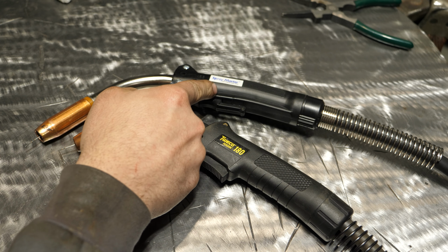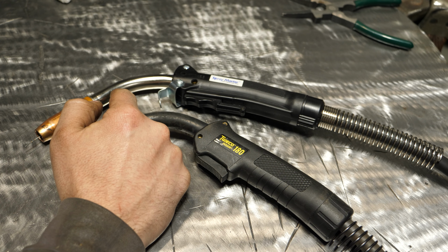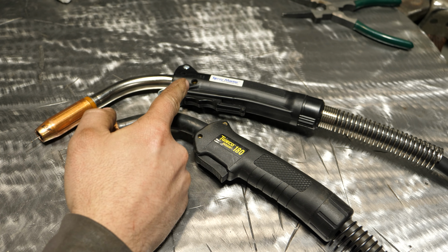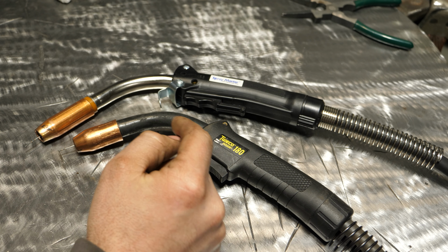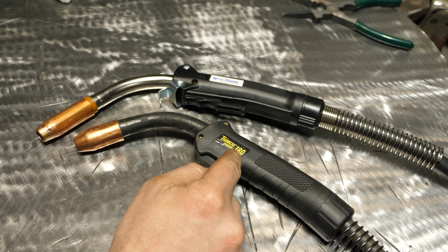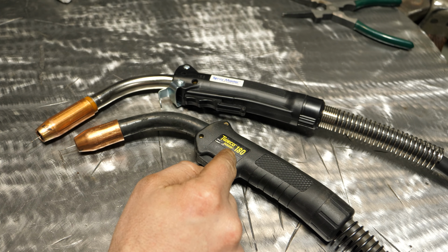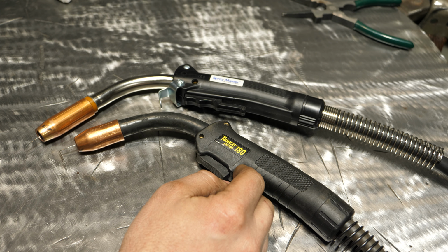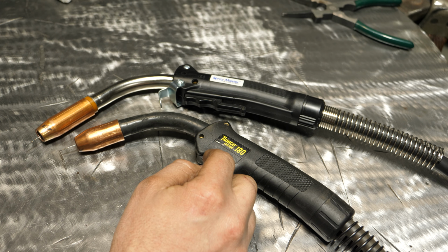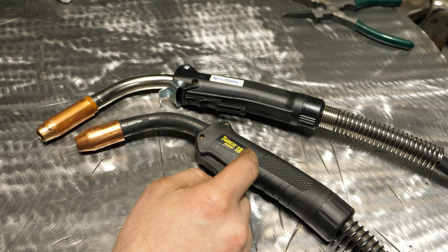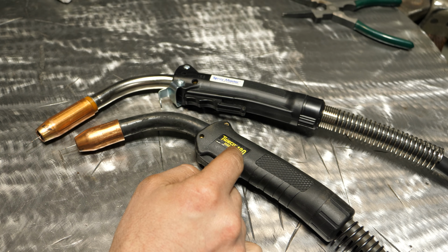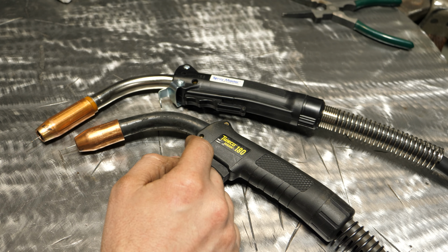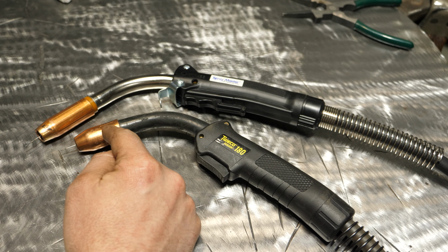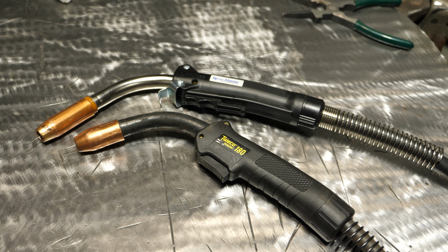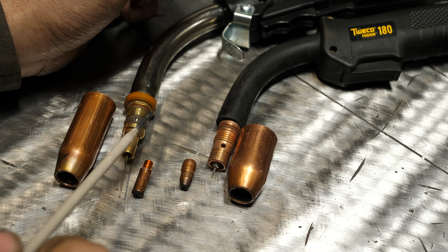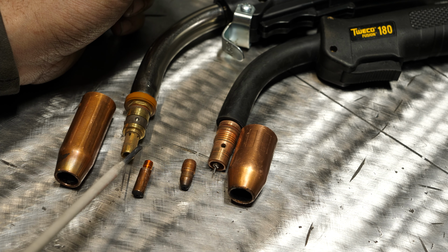So not only is the power cable feeding this bigger, but the overall design is basically to handle the high heat of spray arc. If you attempt to spray arc weld at 200 amps with this gun for a significant amount of time, aka more than maybe 10-15 seconds and multiple times in a minute, you're going to end up with component failures on this because it just can't handle the amperage, nor can it handle the heat. And let me show you in the contact tip department the differences. As expected, the components are significantly different.